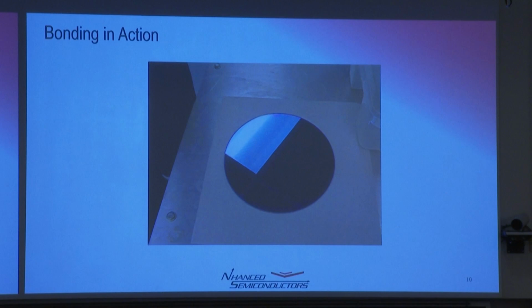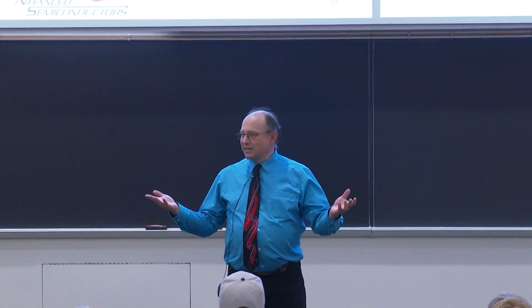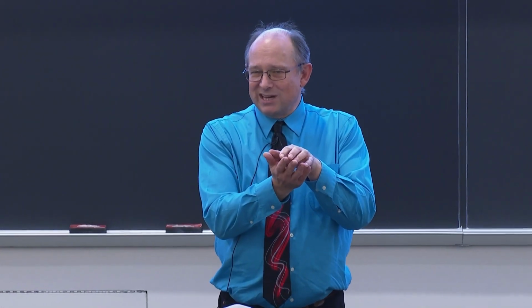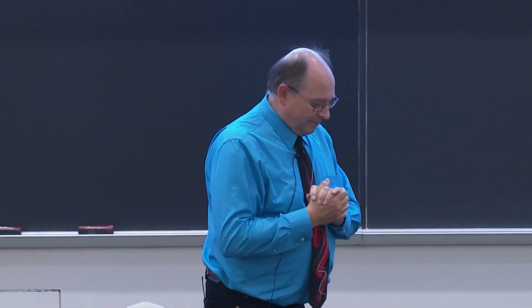When I started the business, we did copper thermal diffusion bonding. The problem is we had to do that alignment in situ and then hold it in place at 300 degrees C. If you're using only silicon, that's not so bad. But if I'm using gallium nitride with silicon, or gallium antimonide with silicon, the problem is their CTE mismatch does ugly things. So it's hard to get them aligned at 300 degrees, and then when they cool, not destroy themselves, because the CTE mismatch causes stress in the wafer.